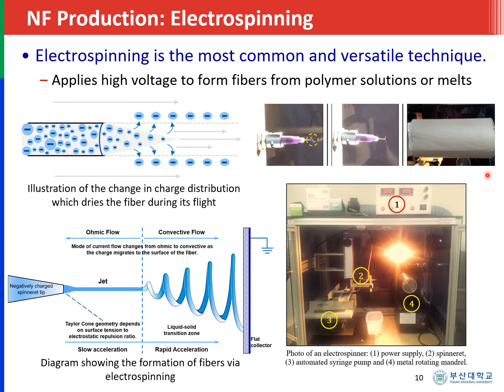This is an actual electrospinning process. So we have the spinneret, and this is the needle, and this is the tip of the spinneret. It's not very clear, but you would see here there's some solidification happening because actually this is not a pure polymer solution. This has some inorganic adsorbents. But you would see here a solid line, and then suddenly a cone-like spray. But actually, these are fibers, which are from the jet. Then the polymer molecules, as I discussed earlier, will repel each other to form fibers until they reach the collector here. So this is actually a mat of nanofibers.